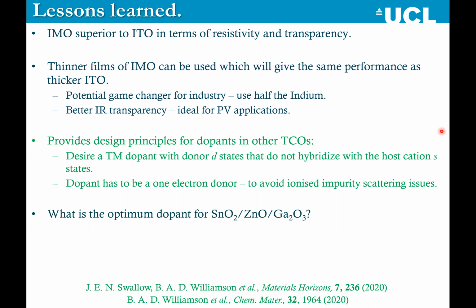So what this taught us, going beyond just IMO and ITO, is that we now have design principles for finding dopants in other TCOs. So if you want a transition metal dopant with a donor D state that doesn't hybridize with the S states of the conduction band, and also you want that dopant to be a 1 electron donor, because you do not want to have ionized impurity scattering issues. You only want 1 excess donor per dopant. So then the open questions were, what is the optimal dopant for, say, tin dioxide or zinc oxide or gallium oxide? So that's what we went on to do next.